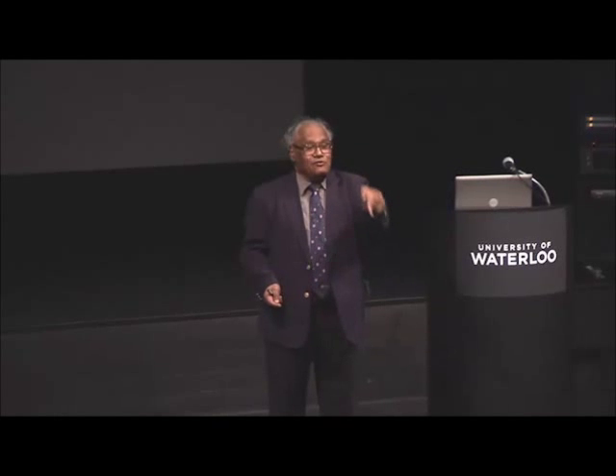And look at this one. That is very nice. When they made it, if you put this single layer graphene on a certain silica substrate, 300 nanometer silica substrate, very easy to make in the lab, it is transparent. You can actually see through it. In fact, that is how I know when my students have made single layer: I can look through it and see whether they made it. It's actually transparent, one layer graphene, okay?